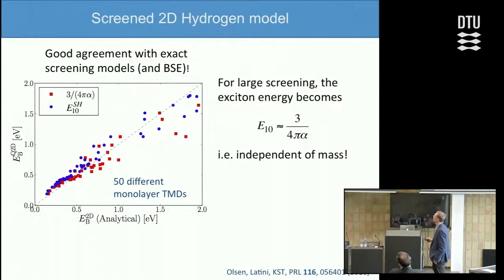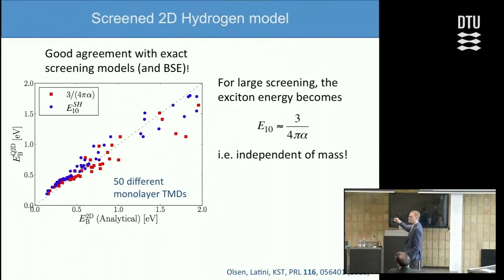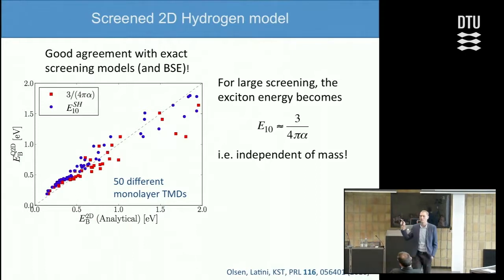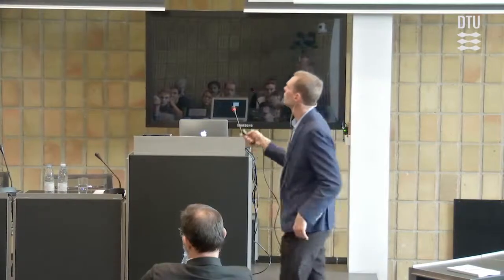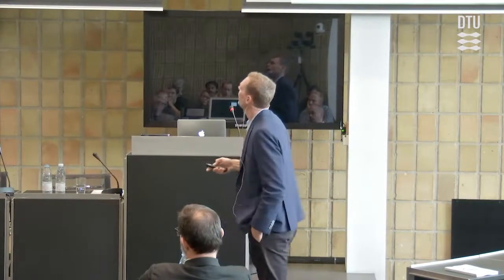A very interesting thing here is if we look at our analytical expression, the mass actually drops out to a good approximation. So the effective mass of the electron and hole doesn't enter the expression for the binding energy. This is very different from 3 dimensions, where the energy is proportional to the mass. So that's a novel two-dimensional effect.